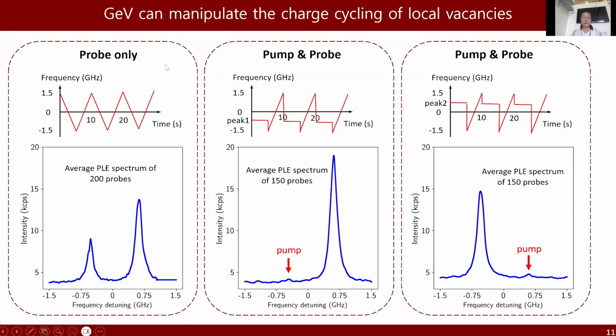We also found that we can actually make use of the GeV to manipulate the charge switching of the local vacancy. The left figure is just a normal PLE scan. We scan the laser back and forth across the resonance frequency, so the two hopping states will show up alternately, and in the end there will be 2 peaks in the average PLE spectrum.